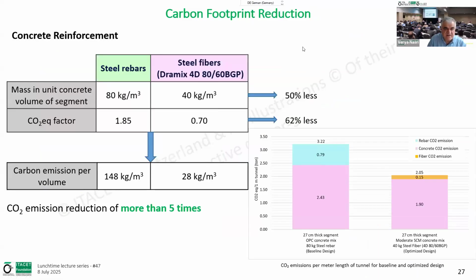So with fiber, our carbon significantly reduces, because you see, if we use fiber instead of rebar, we will have about half of the steel weight, and then the CO2 equivalent factor for fiber is less than half of the steel. So using fiber instead of steel, we are saving carbon by 5 times. Here you see the comparison. Here also we use some SCM, supplementary cementitious material like slag and also silica fume to reduce the carbon from concrete also.